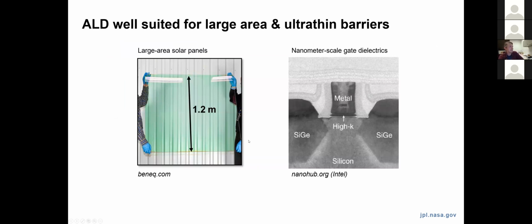And so we thought that since we were working on these ALD processes, and as I'll describe, we started working on ALD processes for metal fluorides, that we could use the same processing to produce protective coatings for aluminum mirrors in the far ultraviolet. So moving away from the detector scale coatings that we're interested in, which at the wafer scale may only be 6 or 8 inches in diameter, to potentially coating things like telescope mirrors, which might be 1 meter plus in diameter. But we had reason to believe that ALD would be well suited for this task as well.